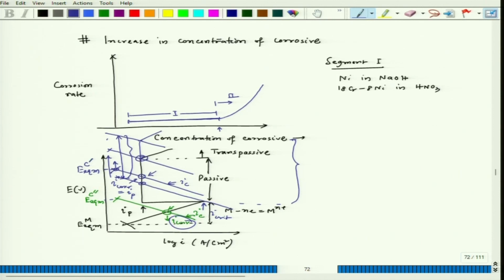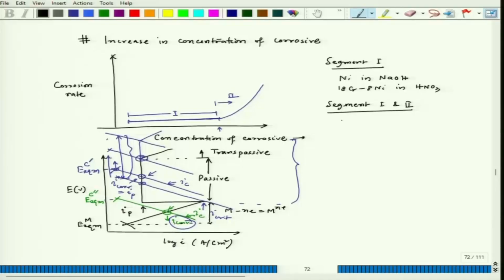Now, in some cases it can follow both 1 and 2. This happens when the material shows a low corrosion rate because of some surface film formation at a lower concentration of the corrosive, but at a higher concentration of corrosive, that film can be soluble. Once the high concentration corrosive dissolves that protective layer, immediately we can see a kind of exponential rise in corrosion rate. One such example is lead in H2SO4.